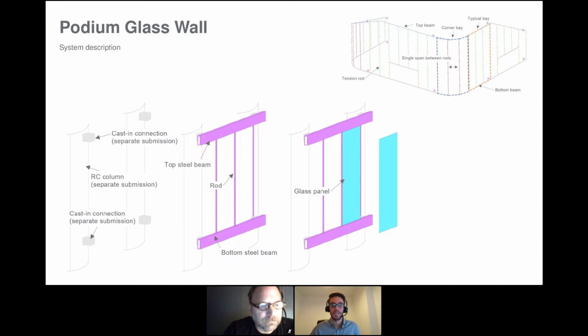So just to give a bit of numbers, the steel beams are quite deep. They are between 1.2 and 1.5 meters deep and between 500 and 700 millimeters wide. This rod system is actually quite minimal, because the typical rod is 52 mm by 45 mm, a rectangular bar made of high strength stainless steel. The glass panels are made of four plies of 12 millimeter thick glass, fully toughened outside and strengthened inside, with the center glass plus interlayer to improve the structural performance.